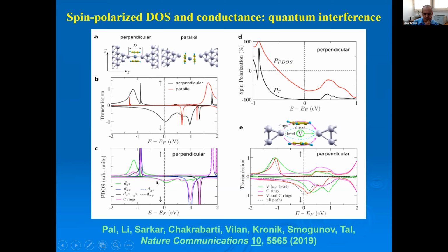The perpendicular scenario does indeed come again with a significant spin polarization in the density of states. But there is one final significant riddle here, and that is that if you look at the polarization in the transmission, which is this block D here around the Fermi level, it can be as much as 100% ideal polarization, even though the polarization in the density of states is not that high. It's only around 60% or so. So the final riddle for us was, how is it at all possible that the polarization in the transmission is actually higher than that suggested by the density of states? Usually it's the other way around due to some scattering. So here it's not only not lower, it's higher. Turns out that this is an interesting quantum interference effect.